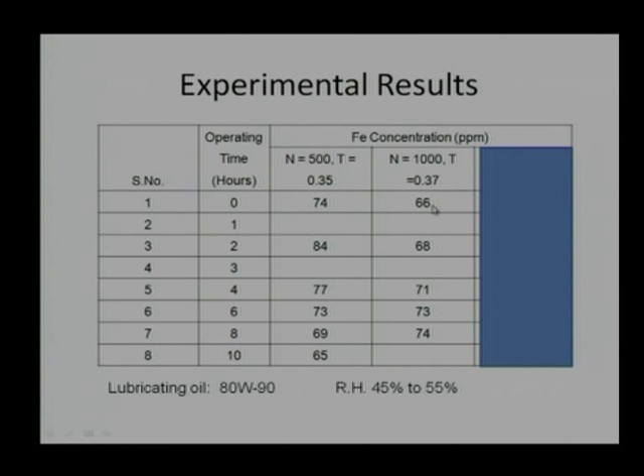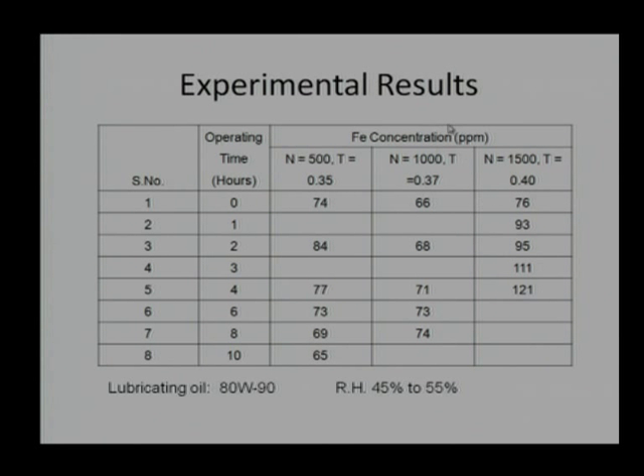But as we are increasing the number of operating hours, we are finding more and more particle percentage coming in. Either the filter system is not working well, or something else is the problem, or another possibility is that at high speed there is high temperature, some flash temperature is happening, or chemical additives, the EP additives, are reacting with the surface, corroding the surface and then removing the top asperities. That is why the percentage is increasing. To confirm that, we increased the speed also, say from 1000 rpm to 1500 rpm, keeping almost the same load, no change in the load as such. This is happening because of the misalignment or some inaccuracy in the surface. Now, what we are getting over here is that this percentage is continuously increasing.